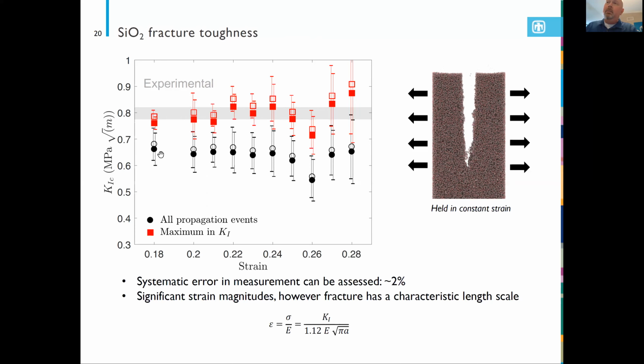Going back to that systematic error, I can assess that now that I've calculated my K2 values, my K1 values, and my T-stress. In all cases, it was about 2% overshooting in terms of results. So I think that's a very nice result for atomistic modeling, where our elastic properties slightly differ from experiment, but our fracture toughness can bracket experimental results very nicely.